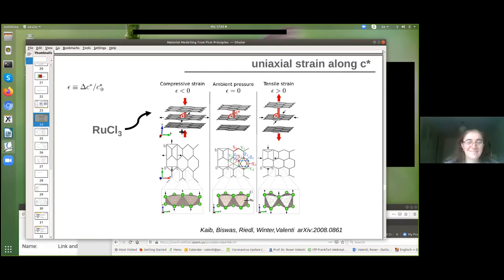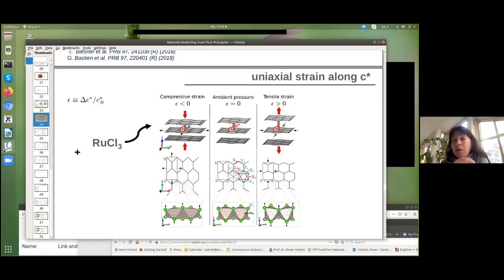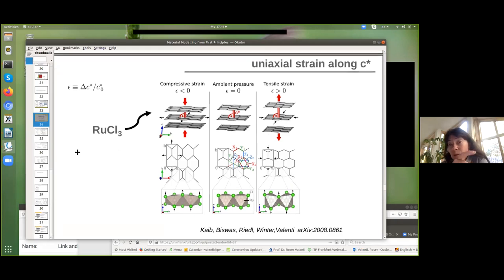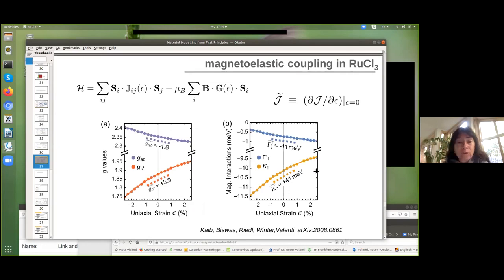Two people have raised their hands, so Natasha Perkins and then Sasha Chernychev. Roser, I have a question. When you were showing the values for the couplings in the second part, for example, the dependence on the strain, these values for the Kitaev interaction and for gamma were very large, like 40 something. Yes, yeah. So this is the slope of the Kitaev interaction. So what I'm showing here, that's why I put the tilde.